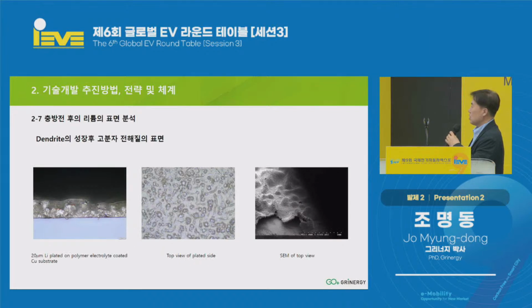And especially the high polymer with the 20 micron plated, we tried to once again analyze the lithium. And you can see here the surface of the lithium after charging and discharging, the surface of the polymer electrolyte after growth of the dendrite is shaped like this. Of course, 20 micron lithium plated on gel polymer coated, and it is concentrated to one side, and it grows not consistently, but with a different shape. And when we get rid of the dendrite, we take a view of the plated side. The membrane is well protected. And of course, it can be penetrated, but still, my view is that if we keep testing, we will definitely find the solution. So the research is going on, and using new ceramic or other composite, we will be able to come up with better test results.